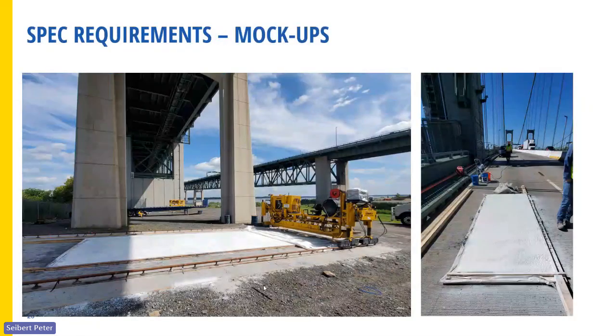The project also required mock-ups. Here we're just showing the 2 mock-ups. One of them is done below the bridge, and basically we're required to simulate that we can meet the 4.5% slope, but actually we did set it up for 6% just to make sure that the material can hold in place. This is very important that we're trying to tell other owners and designers. Mock-ups are very critical, because still there's not a lot of contractors out there that have a lot of experience, and always use the equipment.